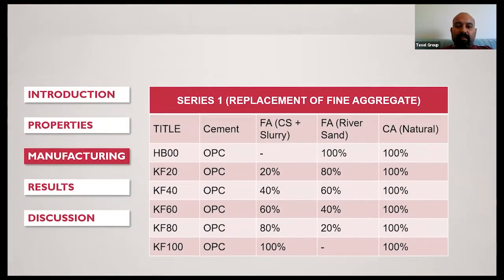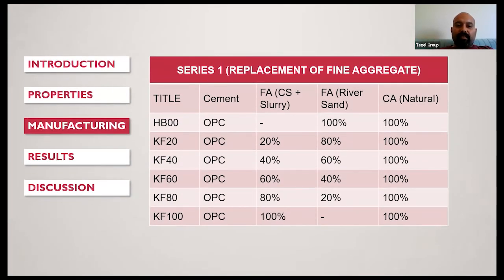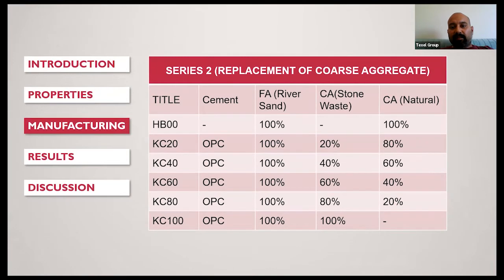I tried replacement with two series. In series one, I replaced fine aggregate with crushed sand at intervals of 20, 40, 60, 80 and 100%. In series two, I replaced coarse aggregate at the same regular intervals of 20, 40, 60, 80 and 100%.